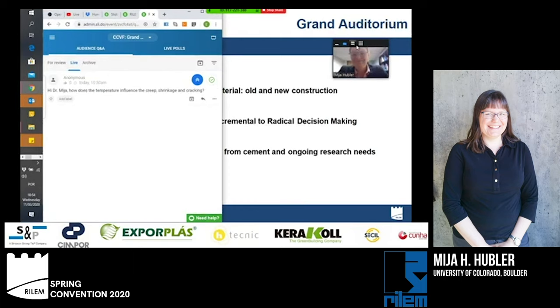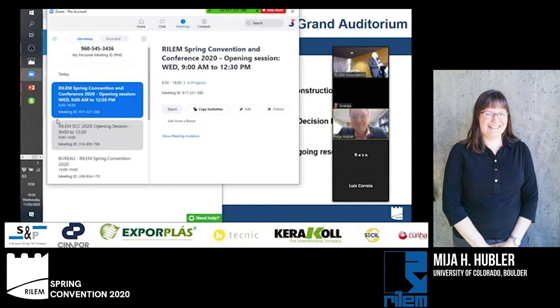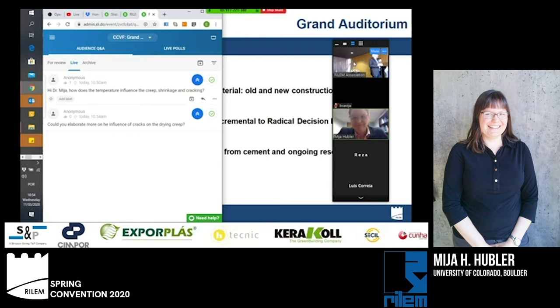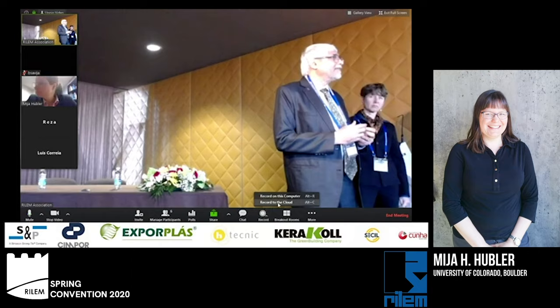Yes, there is one. I'm Ravindra Getu. Thank you again for a very nice talk, Mija. I wanted to ask your opinion about two aspects that you touched upon. One is the cracking due to shrinkage and the aggregate effects. Now, as we are going to higher grades of concrete and water cement ratios are almost systematically less than 0.4, do you anticipate that the autogenous shrinkage of the cement paste will produce cracks around the aggregates? And is that something that we are studying or not yet?